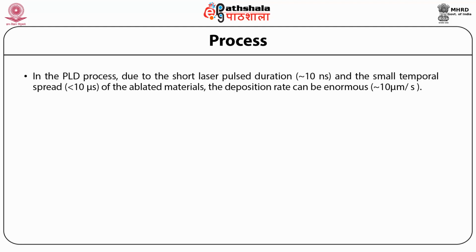In the PLD process, due to the short laser pulse duration of the order of 10 nanoseconds and the small temporal spread of less than 10 microseconds of the ablated materials, the deposition rate can be enormous, of the order of 10 micrometer per second.